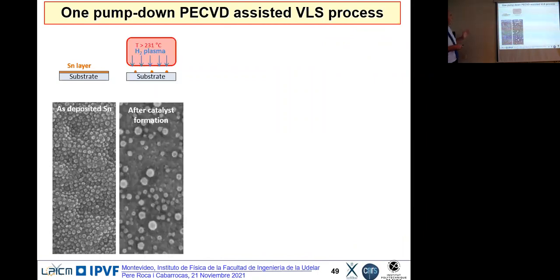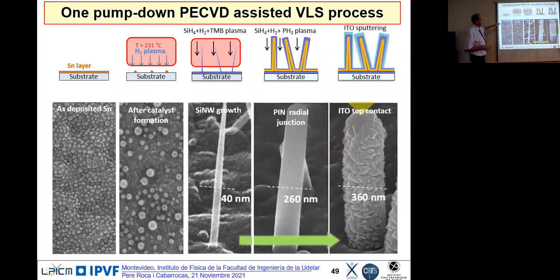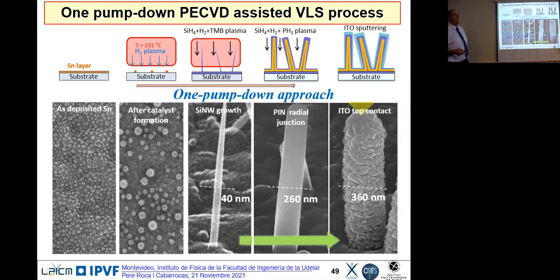So we have growth, and so it took time to get the result. In the meantime, we knew that we can grow nanowires, as explained before, by putting this thin layer, exposing it to the hydrogen plasma to form the drops, moving to silane hydrogen TMB to make a p-type nanowire, 40 nanometers in diameter, then covering this nanowire in a silane plasma with intrinsic amorphous silicon. You have a conformal coverage of this device, and at the end you put the N layer, so you put a little bit of phosphine, and end up by putting ITO to have the top contact. And so this is one nanowire solar cell in one process.